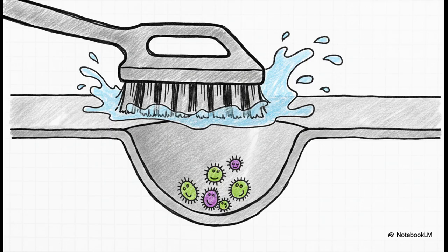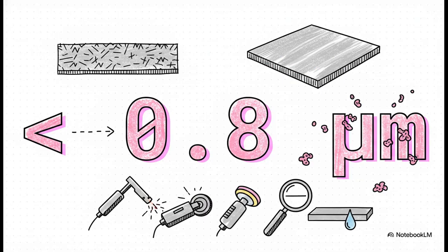It essentially acts as a permanent safe harbor for bacterial biofilms. And once you ensure full penetration and grind that weld completely flush, you're still not done. The surface finish has to meet strict requirements. Specifically, Ra is less than 0.8 micrometers. This exact average surface roughness is absolutely mandatory to prevent soil adhesion and guarantee the surface is fully cleanable.